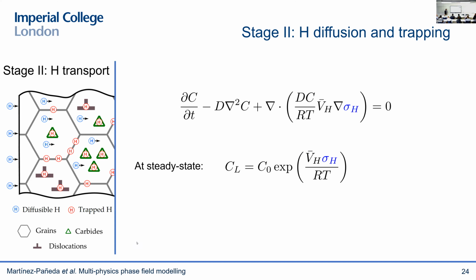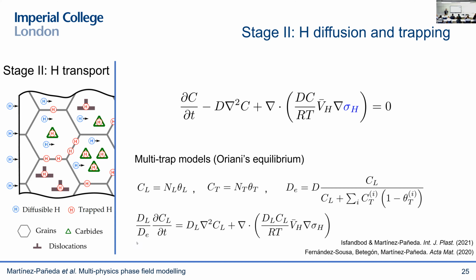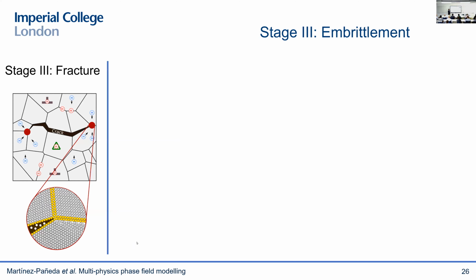But there's also one other thing that you need to take into account. Hydrogen not only travels freely through the crystal lattice, it's also sequestered or trapped at microstructural defects such as grain boundaries, carbide, dislocations. So we have developed more sophisticated models that are able to account for this and that also introduce more couplings with the mechanics because your number of dislocations will change as you deform your metal. Anyway, once you know where the hydrogen lies, when and where, then you can predict the fracture.